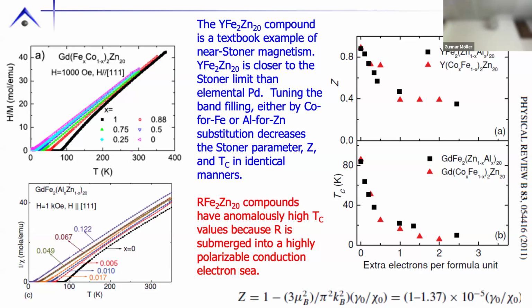It's almost ferromagnetic. And in this case, what happens when you drop a rare earth into this highly polarizable matrix, it orders at a higher temperature than the others. And you can see the similar dilutions here for the gadolinium iron, cobalt, zinc 20. I can have my TC drop as I'm losing this Stoner parameter, and I can do the same thing for zinc. This I was very proud of because we can do two types of very different substitutions, and all of the physics maps onto this.